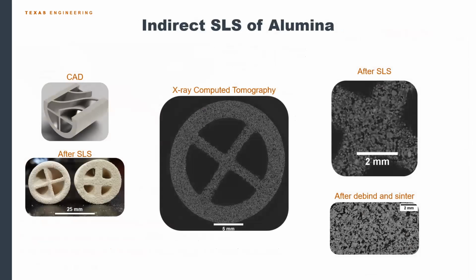As I mentioned, with the indirect SLS process, we're able to tune the porosity. And porosity can be beneficial for some applications, especially on the surface. An example application would be catalysis, where you want the surface of the solid to interact with some liquid or gas. So in the indirect SLS process, we're able to tune that small scale porosity on the surface, which I'm showing with the X-ray computed tomography images. You can see there's some porosity down at the particle scale, on the order of microns.